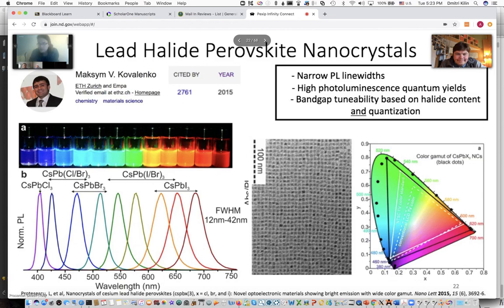And these white regions represent the conventional or standard displays for televisions on the market now. So those are the color purities that they can get from materials, whereas these black dots represent the color purity of these lead halide perovskite nanocrystals. So essentially the main takeaway is that the blues are bluer, the greens are greener, or they're a lot greener than what you can get with other technologies, and the reds are redder even.